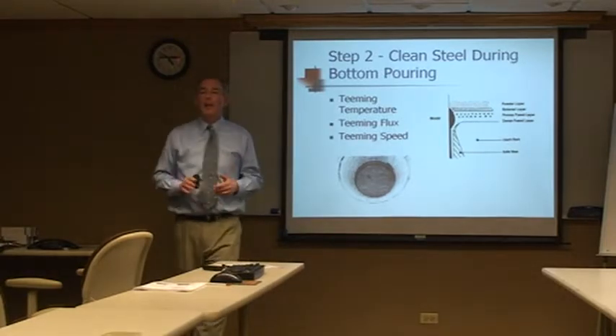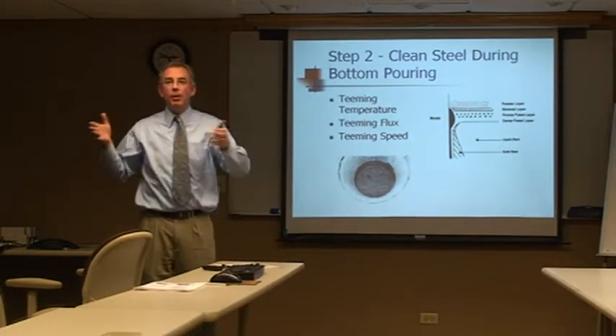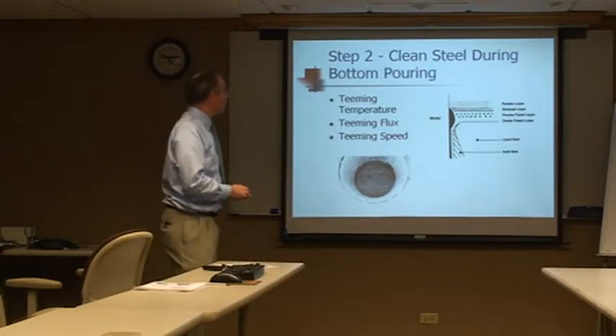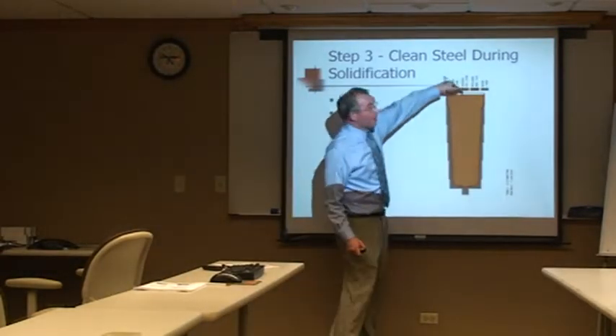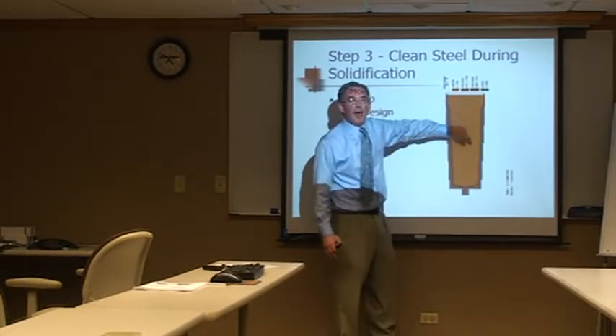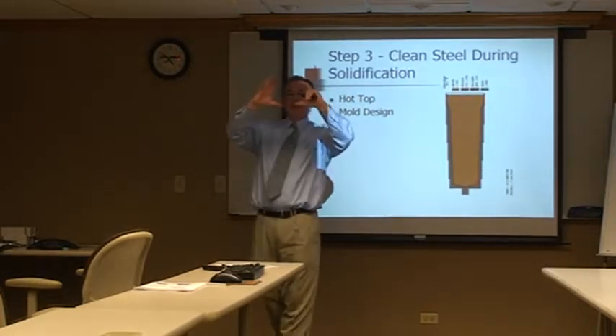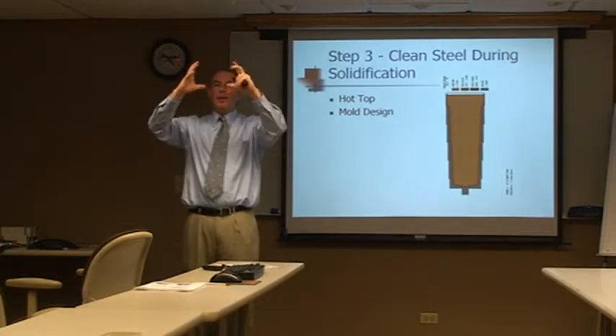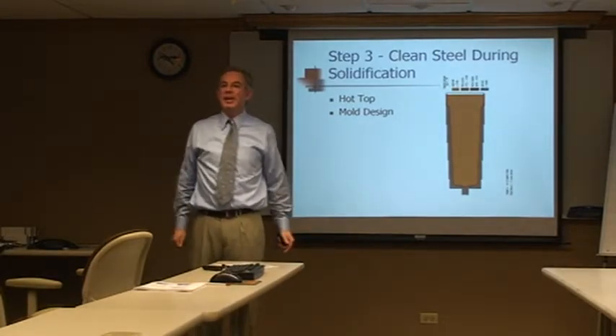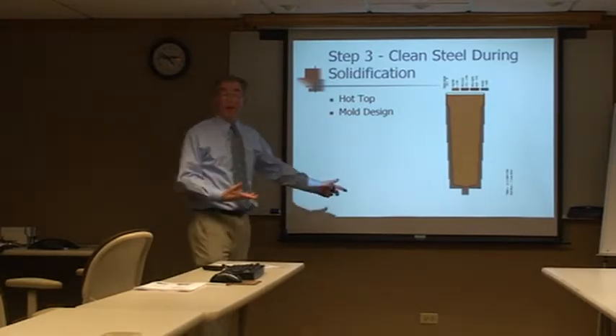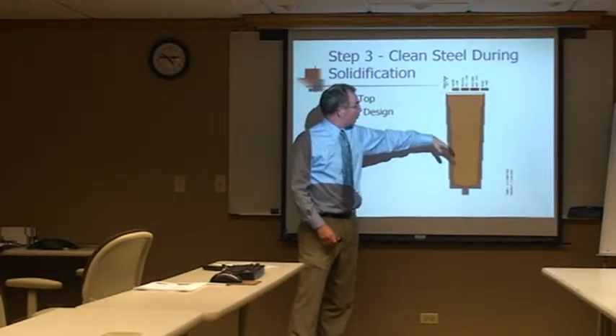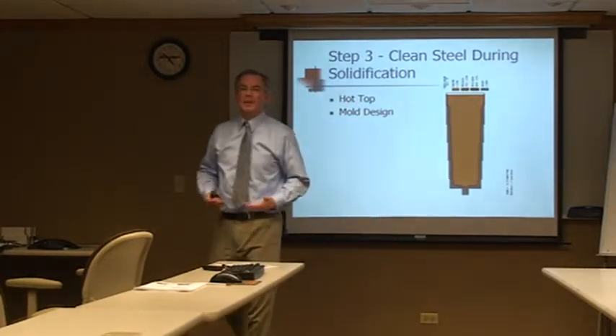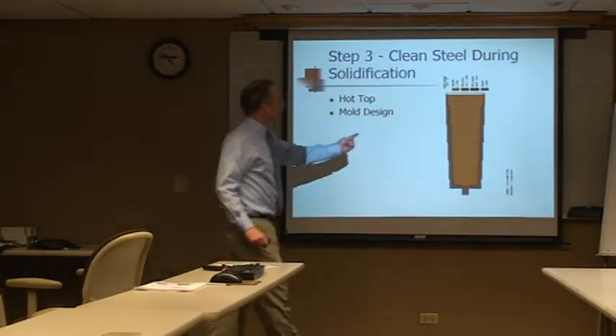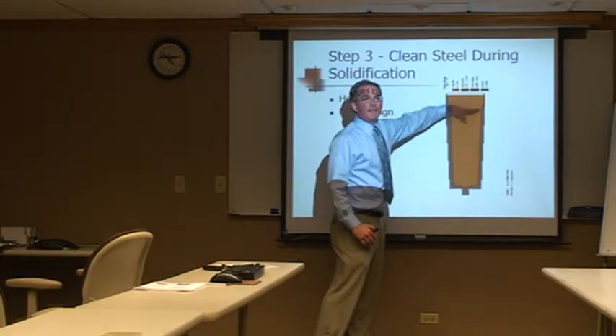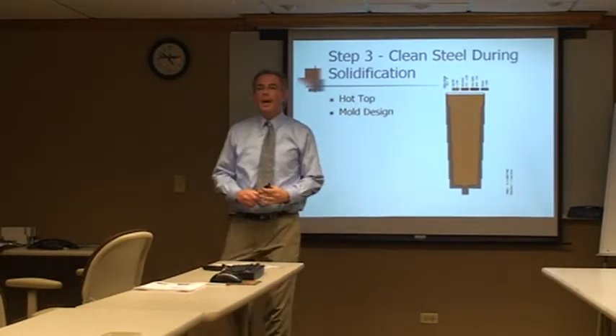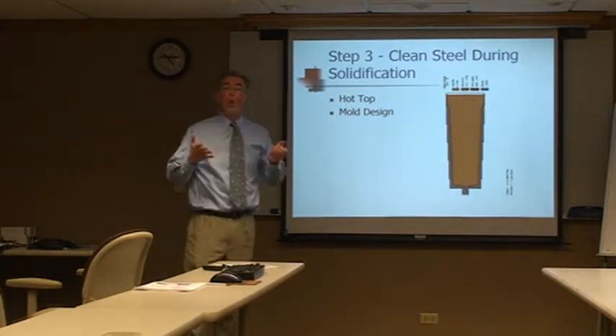The reason we need the hot top is because the steel, we talked about it earlier, shrinks when it solidifies. So if we did not have a hot top, the ingot that we deliver to Scot Forge probably will have a primary pipe cavity about as big as your head at the top, and you might lose 50% of the ingot, you might lose 60, you might lose 40. It would be pretty variable, and it would be pretty unruly to try to make product consistently out of. So what we do is we put this hot top up here. It slows solidification and helps control the discard. We control what we're going to scrap.